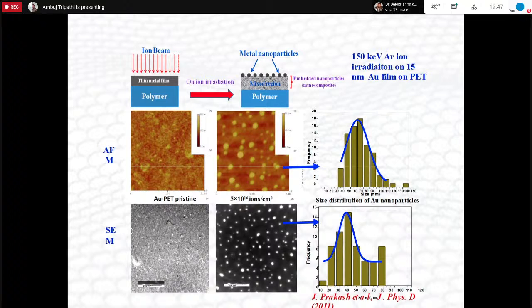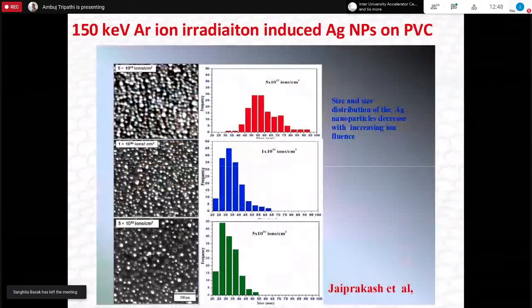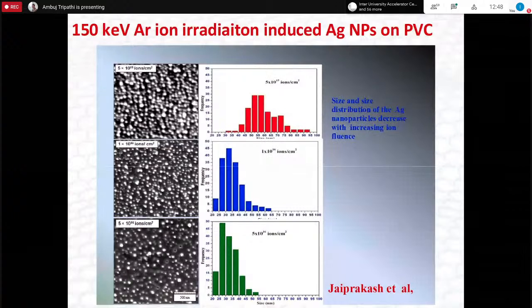And about these nanoparticles on the surface, as I said, with the ion beam effect, you should be able to do it with different ion beams. So this was on gold, irradiated with 150 keV argon. Another with 150 keV argon was done for the silver nanoparticles, shown on PVC. Again, as you irradiate and increase the fluence, 5 into 10 to the power 15, 1 into 10 to the power 16 and 5 into 10 to the power 16, the size distribution decreases and you can get this nanoparticle formation on the surface.